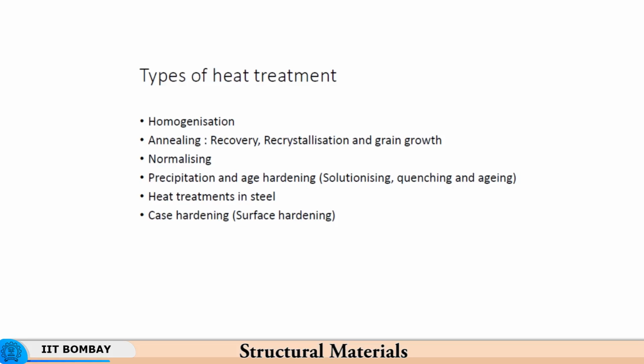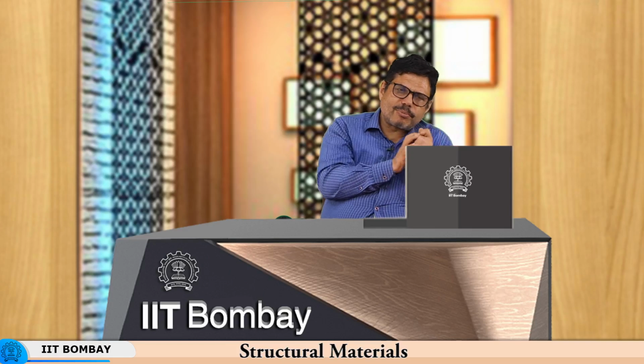So, the idea here is not to homogenize the chemical composition, but to result in either recovery, recrystallization or grain growth. Recovery means you relieve all residual stresses, or the stresses which might have been induced in the material during the course of manufacturing. So, how do you do stress relief annealing? When you heat the material to a high temperature, you are bringing down the yield point of the material. Now, the level of these residual stresses can be higher than the yield point, which means that the residual stress gets the material into the plastic deformation range, because the residual stress level is higher than the yield strength of the material. Why? Because you have heated the material and brought down the yield strength.